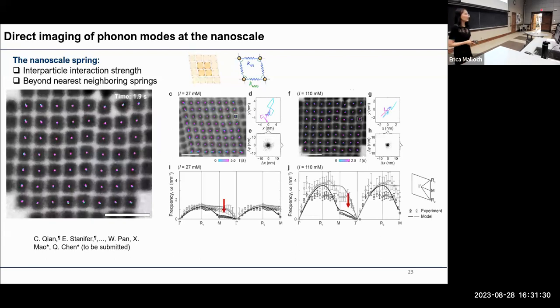And there are 2 aspects I'd like to highlight. The first is you will always have this low energy branch in the phonon spectrum for both of the 2 Maxwell lattices. And that corresponds to the soft modes, corresponding to the large scale lattice rearrangement.